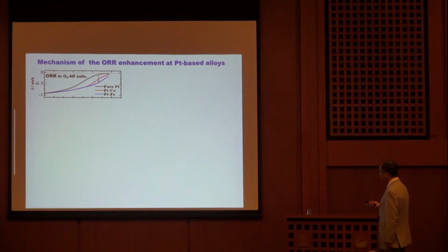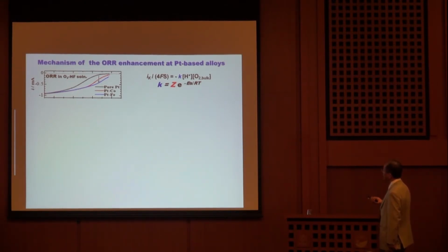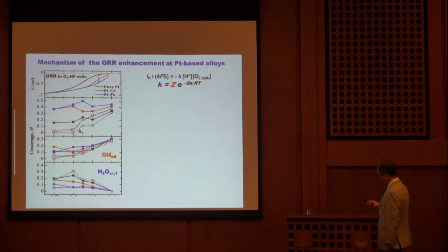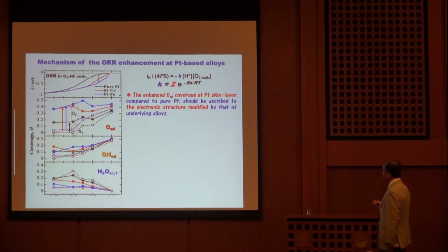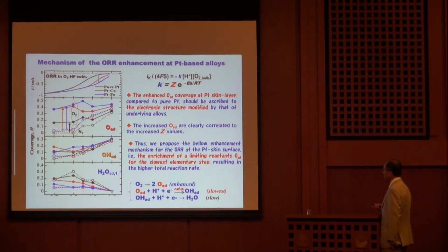And so now we discuss the mechanism of enhanced catalytic activity shown by this equation. The enhanced oxygen coverage at the platinum skin layer compared to pure platinum should be ascribed to the electronic structure modified by that of the underlying alloys. And the increased oxygen species are clearly correlated to the increased Z values. And thus we propose the below enhancement mechanism for the oxygen reaction at the platinum skin surface.